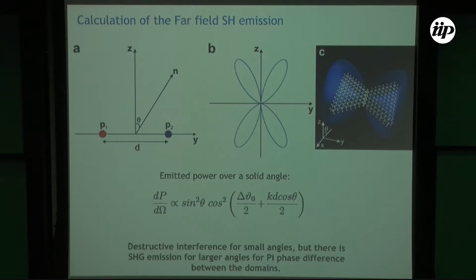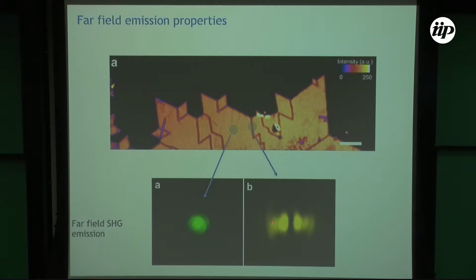All right. In order to understand this, we did a very simple calculation. We just consider two dipoles that are separated by a distance d. The MoS2 is in the y plane here, and the z direction is the out of plane direction of the MoS2. Then we calculated the emitted power over a solid angle, where theta is the angle between the z direction and a vector n over here. The emission pattern looks like this. For a small angle, small theta, you have destructive interference, but when you start to increase this angle, you can have constructive interference. So this emission with larger angles means that we have some constructive interference in the grain boundaries. The destructive interference only occurs for small angles.